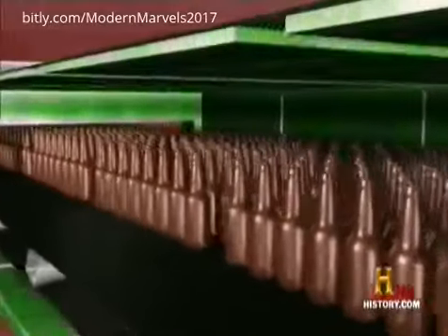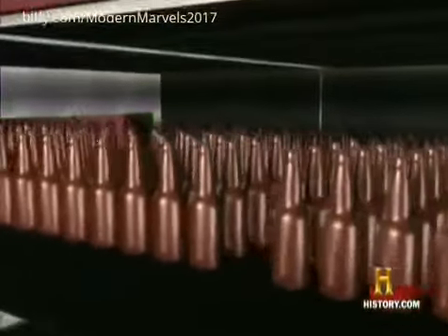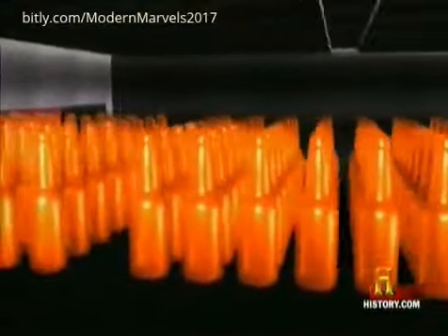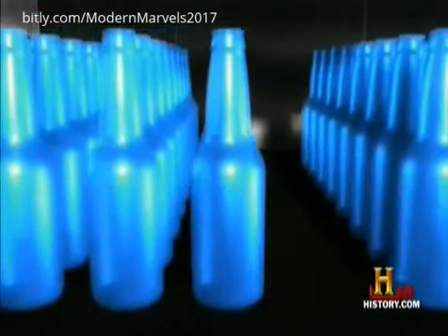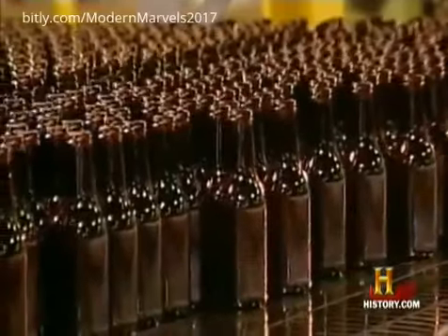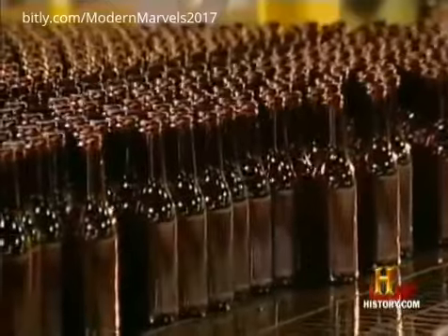Therefore, the formed containers are loaded into an annealing leer, where their temperature is raised to 1,000 degrees, then reduced gradually to below 200 degrees. This reheating and slow cooling eliminates the stress in the containers, making them stronger and more shock resistant.